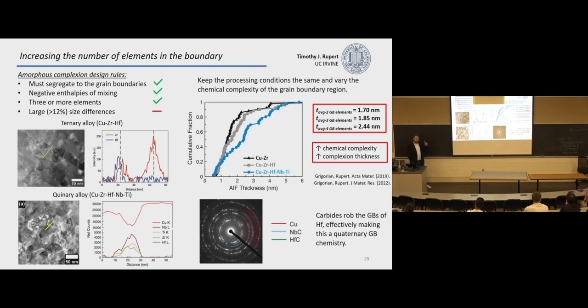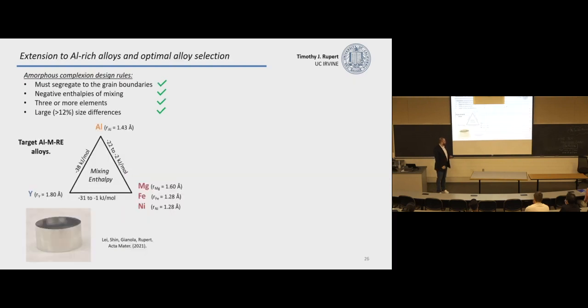And remember, increasing complexion thickness means I can sustain higher strains and more dislocations. So there's a reason I care about that. It's not just that thickness is higher. No, it's better properties. We've recently been looking at a system that actually checks all of these boxes. So it's something that also has large atomic size differences between all of the atoms. It's actually relatively hard to find things that can address all of that.